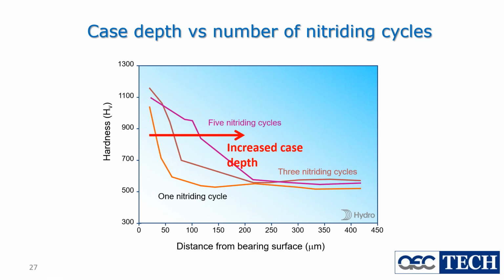A nitrogen atom, which is sitting just here, when it gets hot in the next nitriding cycle, can go to the right, it can go to the left. It randomly moves. But the ones that go to the left, once they break this surface, will meet another nitrogen atom, boom, nitrogen molecule, they're lost to us. The ones that go inwards just increase the case depth. They just push the case depth inwards.